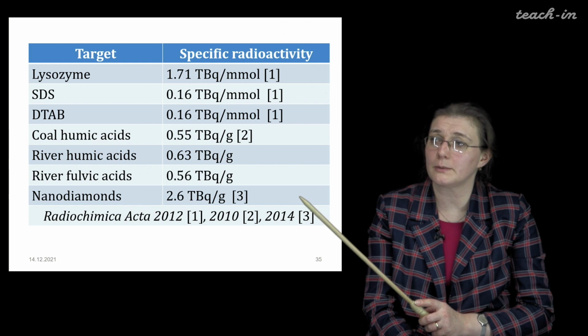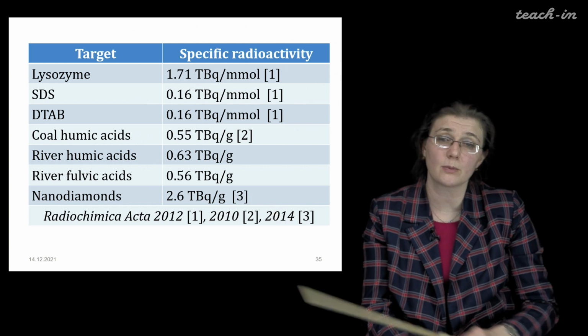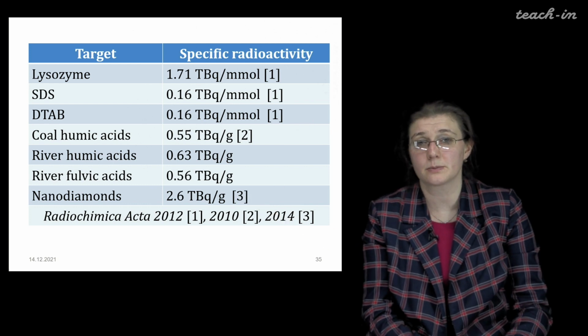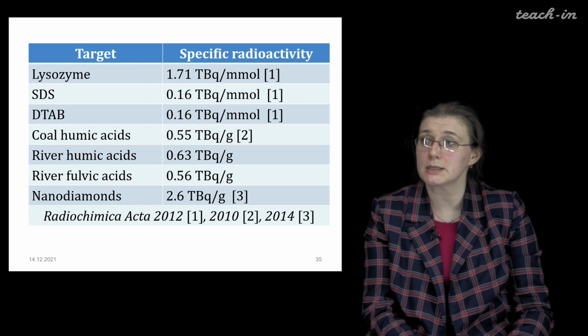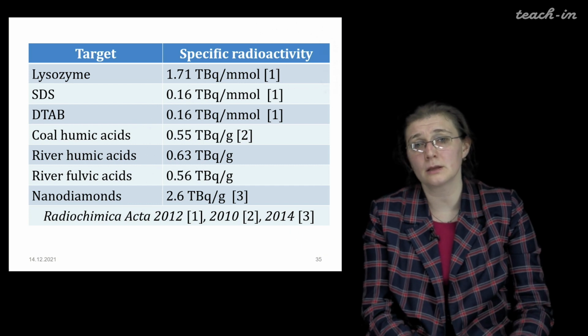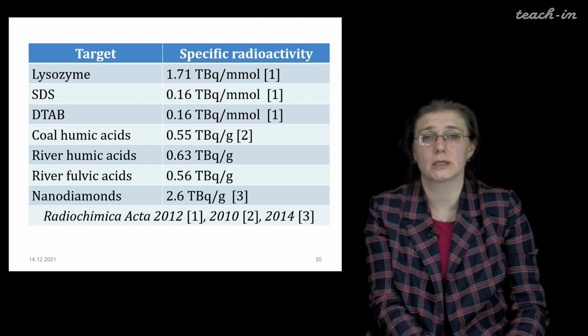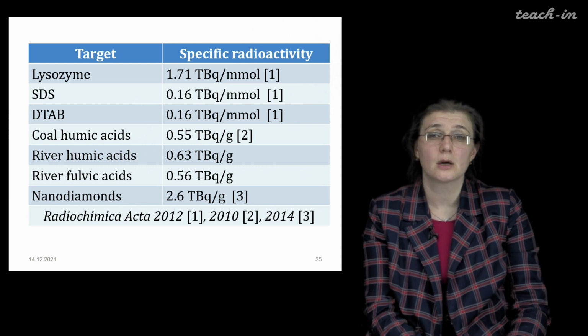Finally, this method is applicable to introduce a radiolabel into carbon-based materials, including carbon-based nanomaterials. Here is an example with nanodiamonds, and I also know examples with radiolabels of carbon nanotubes, multi-wall and single-wall nanotubes.